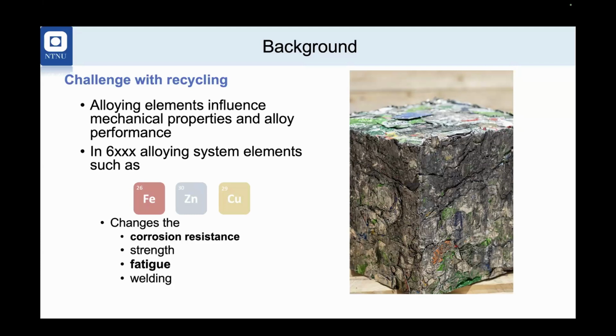For example, there will be a lot of impurity elements in recycled aluminum, like iron, zinc, and copper. If you have the presence of these impurity elements, this can change the mechanical properties. We'll focus on these two mechanical properties, which you see in bold, corrosion resistance and fatigue. Also, Norway has a long coastline, so whenever we consider components for fatigue-sensitive applications, it also comes along with corrosion. So for better design, it's imperative that we consider both fatigue and corrosion hand in hand.